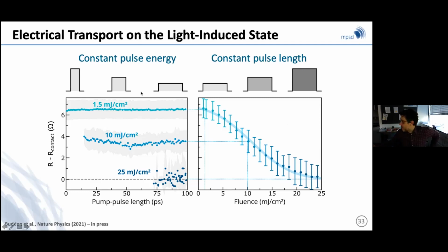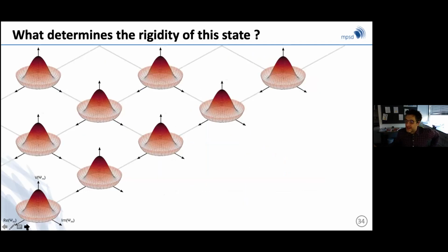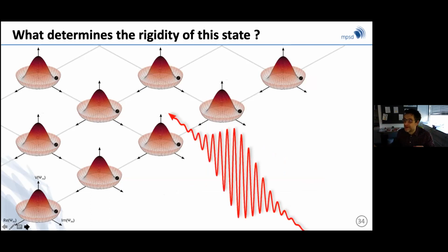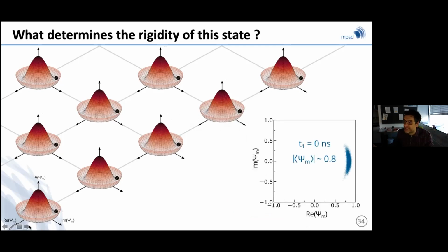And because I want to tell you a few other things, I will not discuss what we believe is the reason for the long lifetime. But basically, I will only say that what we think is that I can imagine a state in which I create this superheated superconductor and then I stop pumping it, and this superconductor relaxes not by charge excitations across the gap, which is probably more rigid, but rather by fluctuations of the order parameter phase, which then diffuses